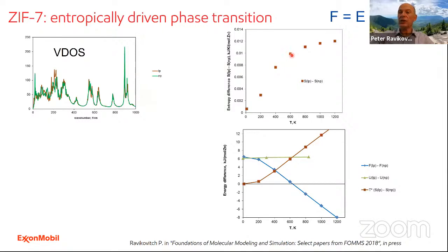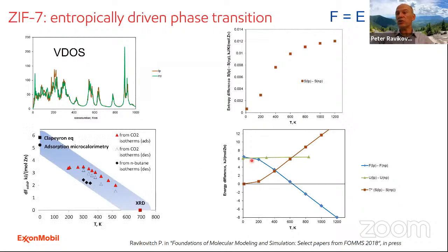And what you can do next, you can plot the free energy. The free energy in this case will be a decreasing function because the TΔS term increases with temperature. And the free energy difference decreases, and indeed shows the transition from the narrow pore phase to the large pore phase. You can look at this calculated free energy versus the free energy which we measured in experiment. There is a very good agreement, really good agreement, both for the magnitude of the energy difference at zero temperature, as well as the transition temperature. It's about 700 K in experiment and about 600 K in simulations.